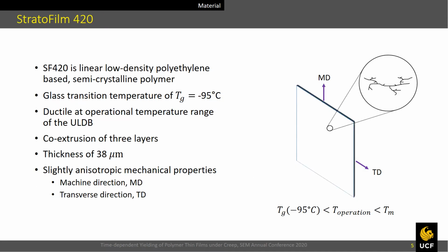The material under study is linear low-density polyethylene based. It's the preferred material over other polymers because of its ductility at operational temperatures of the superpressure balloon. It is manufactured by co-extrusion of 3 layers and has a nominal thickness of 38 micrometers, and it displays slightly anisotropic mechanical properties in machine and transverse directions.